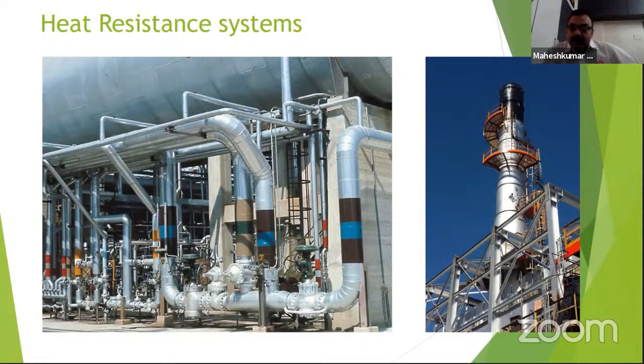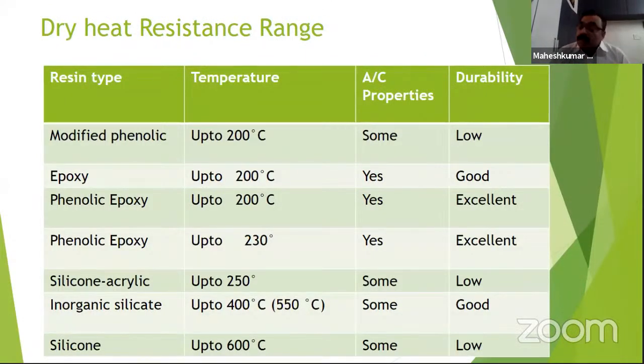The coatings available at this time in the market are either heat resistant or CUI coatings. The heat resistant coatings can be in various forms. They can be modified phenolics, epoxies, or phenolic epoxies. They have certain properties which may or may not give you durability. For example, if you take epoxy, it can have a temperature resistance of up to 200 degrees C.